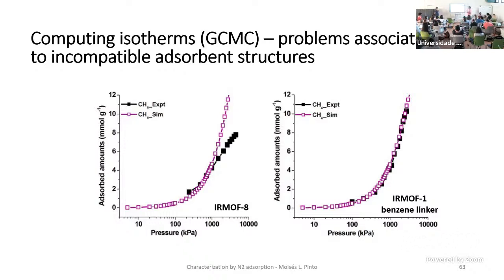So something was not very clear, and the fact is that using the same computational setup for a very similar MOF, where basically the difference is in the nature of the linkers, which in this case is benzene and IRMOF-8 is naphthalene, so very similar linkers, we could, as you can see, more or less reproduce the experimental isotherm.